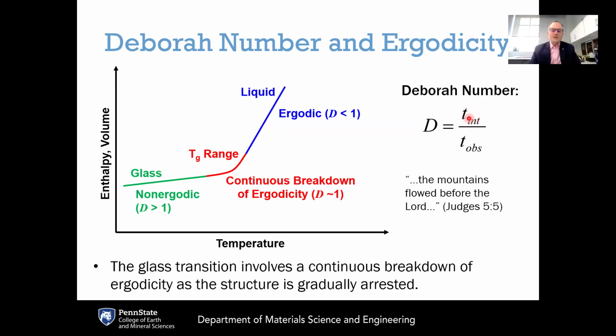Now, as we cool the liquid, the kinetics become slower and slower. This intrinsic relaxation time scale increases by orders of magnitude. Eventually, it becomes of the same order as our observation time scale. And when that happens, when the T internal is about equal to the T observation, then the Deborah number is about 1. And when the Deborah number is about 1, there is a continuous breakdown of ergodicity, because the kinetics are becoming of the same order as our observation timescale. And this corresponds to the glass transition range. This corresponds to the freezing in of the liquid state into the glassy state. And this is really the most fundamental definition of the glass transition: where we have a breakdown of ergodicity, where we have a conversion from an ergodic system to a non-ergodic system.